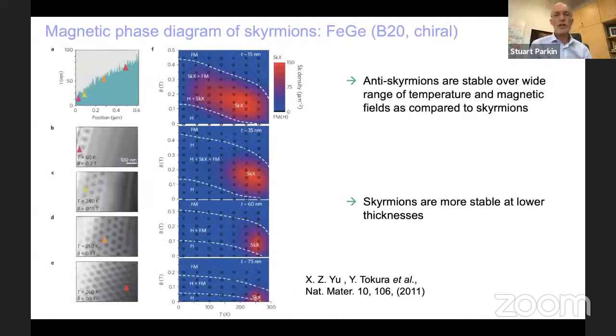And I want to compare that with the archetypical skyrmion system, the B20 chiral system, iron germanium. This is very closely related to the manganese silicon system in which the original discovery of these skyrmions was made by Christian Pfleiderer. This is some beautiful work from Yoshi Tokura's group. And what they're showing is a similar phase diagram. The red regions are where you see skyrmions, and what is plotted is the perpendicular magnetic field and the temperature from room temperature down to lower temperatures. And you can see as you increase the thickness from the top to the bottom, from 15 to 35 to 60 to 75 nanometers, these red regions decrease in size. That's where they see these skyrmions. So the skyrmions become less stable as a function of increasing thickness of this lamella.